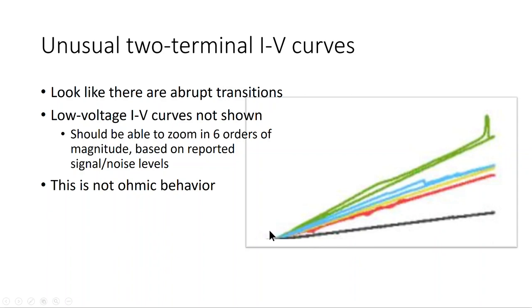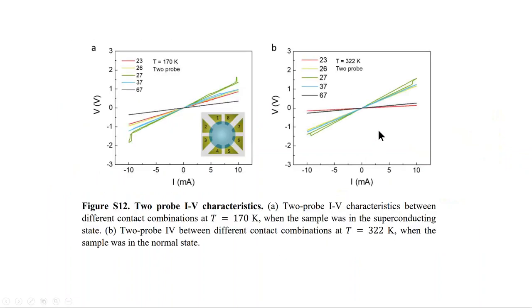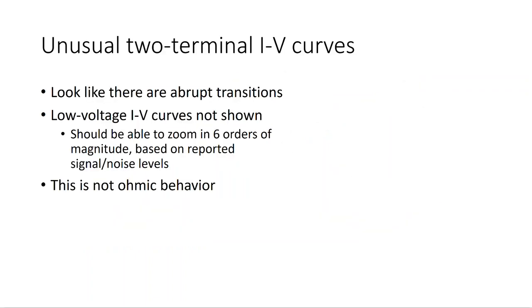This is not linear behavior as they describe, or ohmic behavior as they describe in their manuscript. And also what we don't see are the close-up here. So remember, they can measure nanovolts, and what they're showing here is volts, basically. So they're really not probing in a regime where you might expect to see basically floating leads, voltage leads that could lead to the measurement of zero resistance.